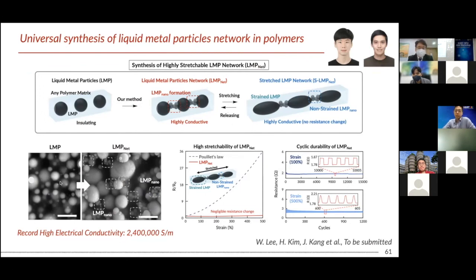Conventionally, if you mix liquid metal particles in a polymer matrix, because of surface tension, they couldn't form a percolation network. So in order to make the percolation, we need to apply mechanical stress to rupture some of the liquid metal particles and leak the liquid metal. But we found that if we make new liquid metal particles in between these two particles, we can make a very nice percolation pathway with very high electrical conductivity.